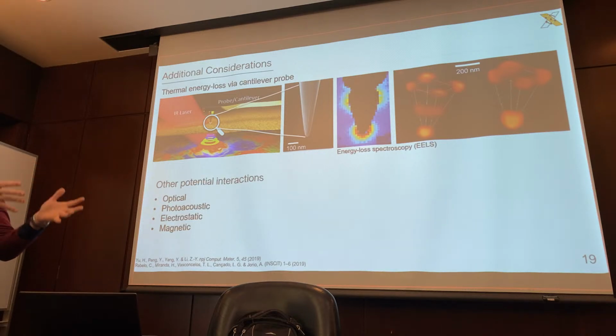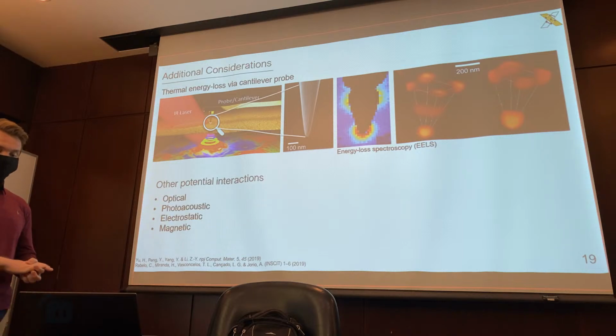You can't do it alone, of course, but it plays a much larger role, say 70 or 80%. I'm just pulling those numbers out of thin air, but I believe it plays a dominant role in actual AFM-IR signal generation. So in that scenario, if you use a regular silicon tip, will you be able to resolve any contrast at all? If it's thermal expansion, you should be able to see it. Then will you be able to measure it, perform AFM-IR? Yes, because they did this without gold-covered tips in the past. That wasn't necessary. It was only more recently where we began using gold-covered tips to maximize that plasmonic effect. So it obviously helps, but it doesn't play the large role as compared to thermal expansion. Yeah, that would be useful to confirm.